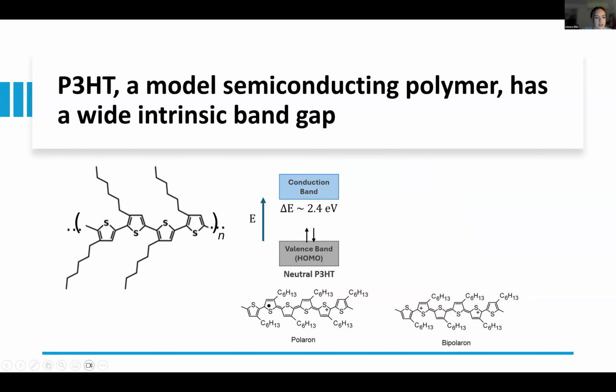So here is the structure of our model semiconducting polymer, which is poly-3-hexylthiophene. It has this conjugated thiophene backbone with these hexyl side chains. And intrinsically, like most organic molecules, it has a pretty wide band gap, which means that there are pretty few charge carriers in the conduction band at room temperature. However, we can improve the conductivity by doping.